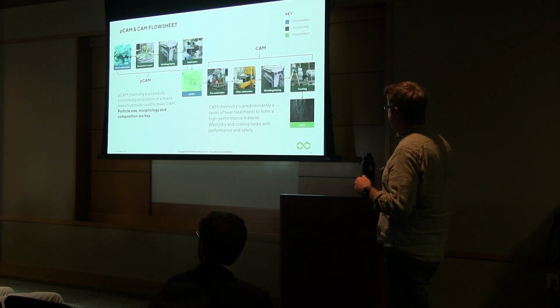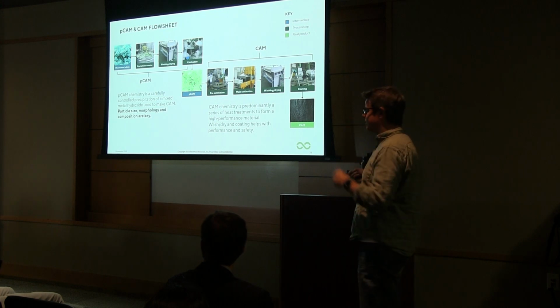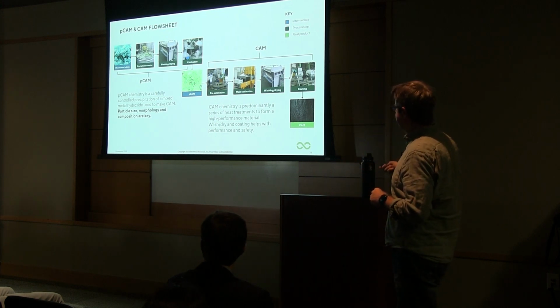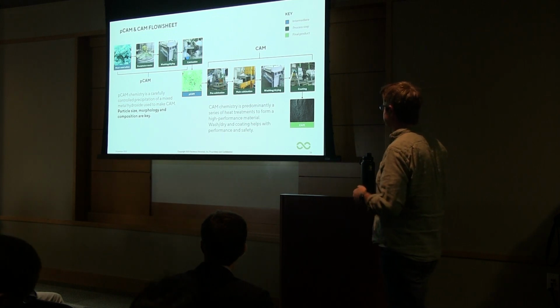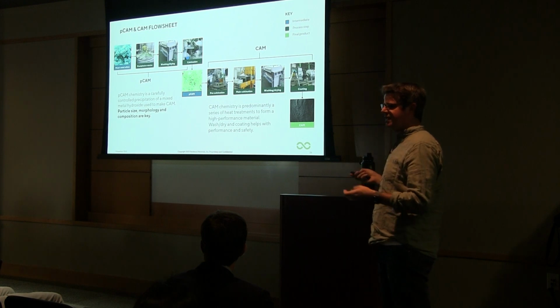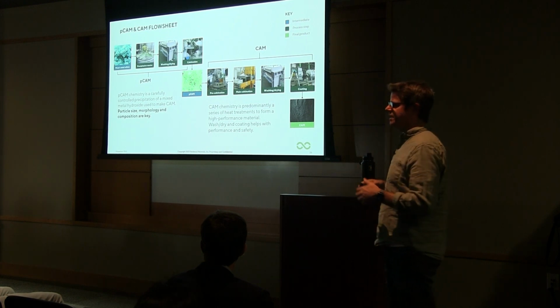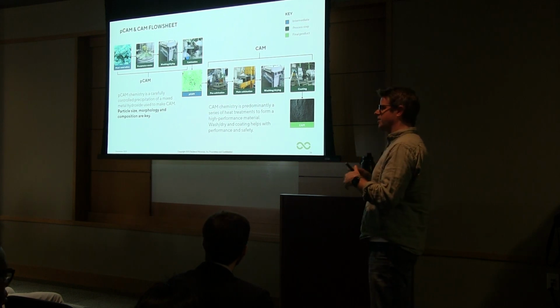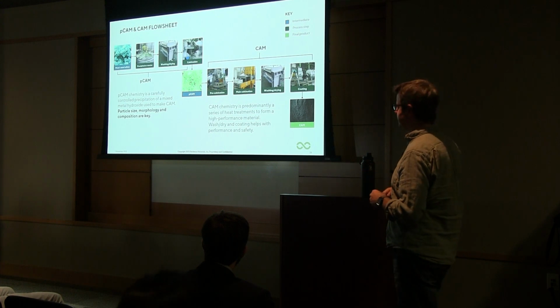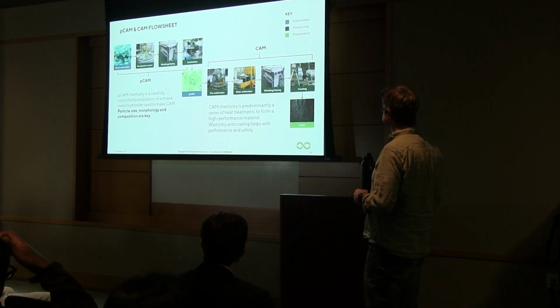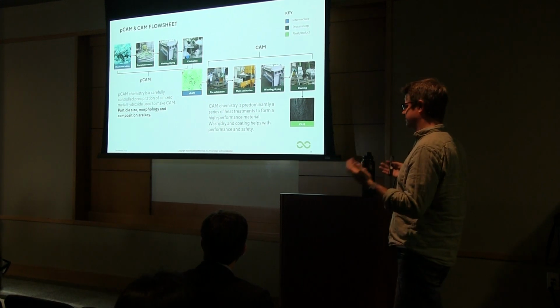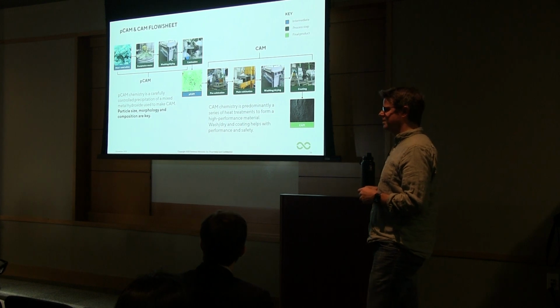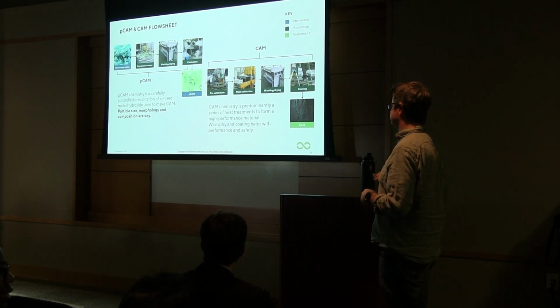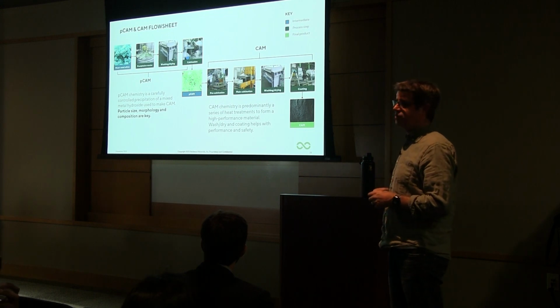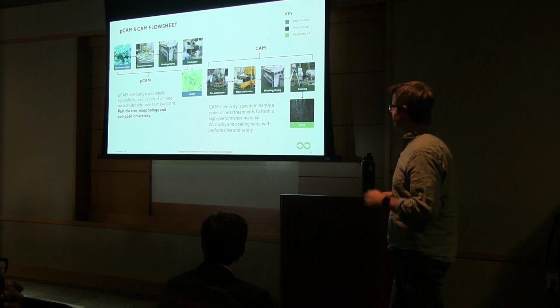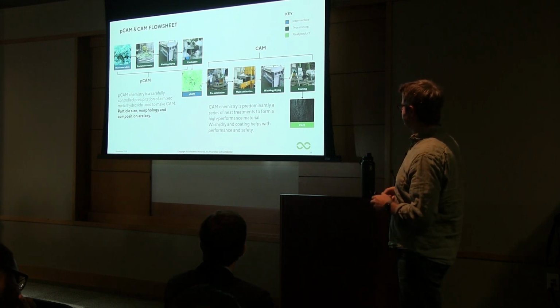With the PCAM, we then pre-calcine it. This is where we start adding the lithium hydroxide. So this is where lithium is added. And then we calcine this in a number of stages, wash out and filter out the excess lithium, and then we perform some coating on the CAM. This refers to coating of the particles, so that this enhances their electrochemical performance in the cells. So PCAM is really sort of a fancy precipitation with sodium hydroxide and ammonium hydroxide, and the cathode active material production is really a series of heat treatment steps. If you really wanted to break it down, my cathode colleagues would probably kill me for that explanation, but that's sort of how it's simplified.